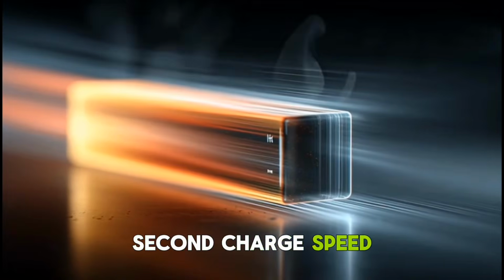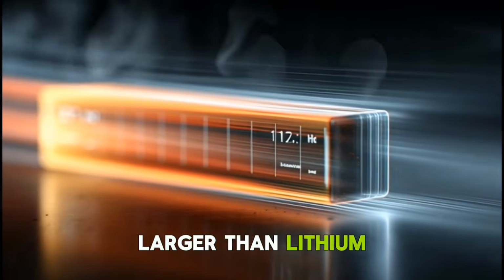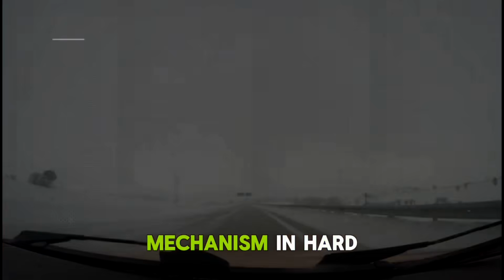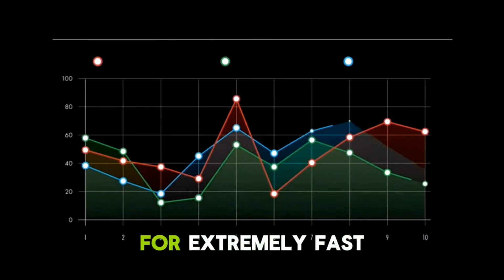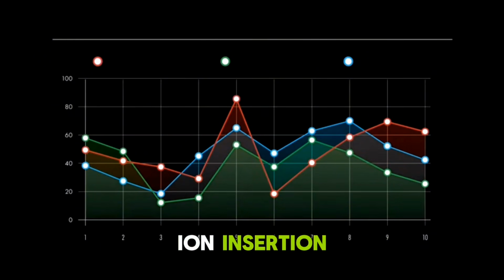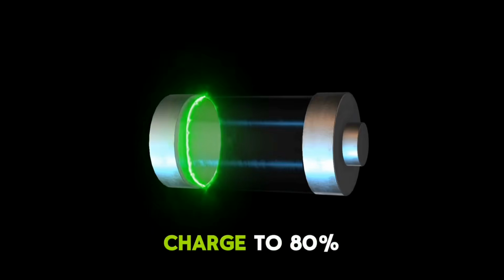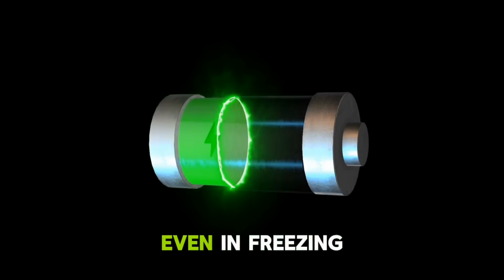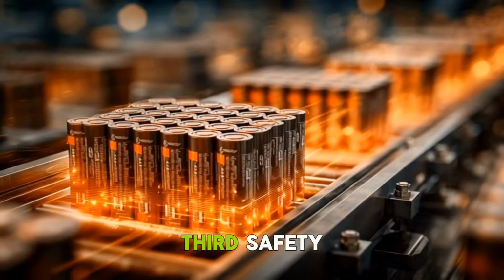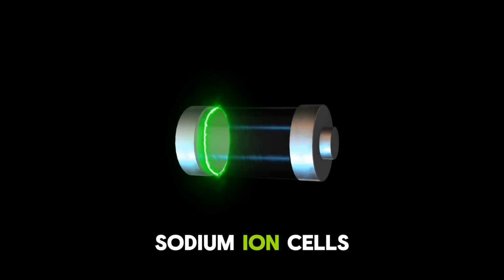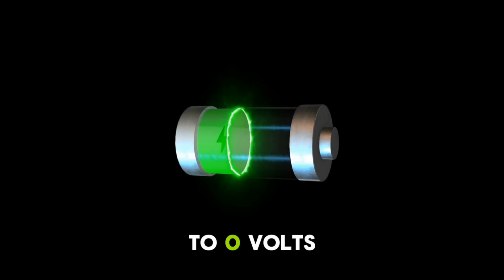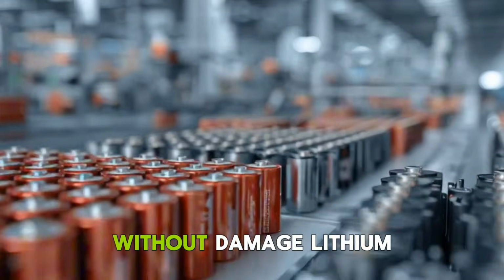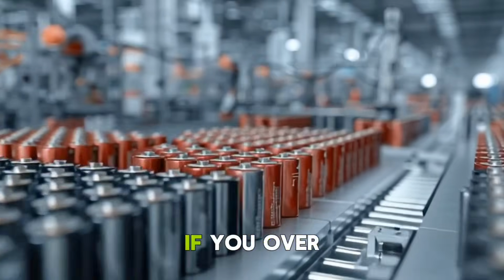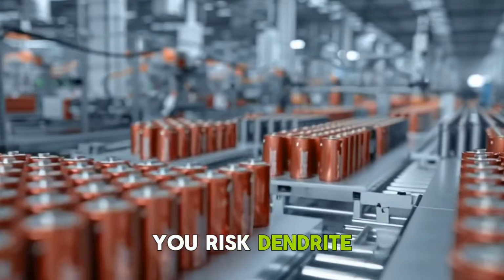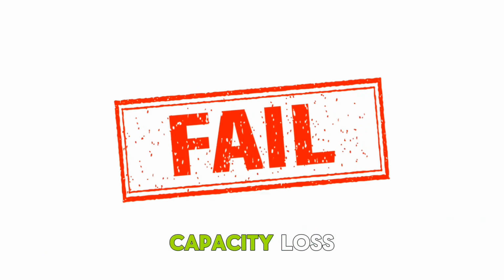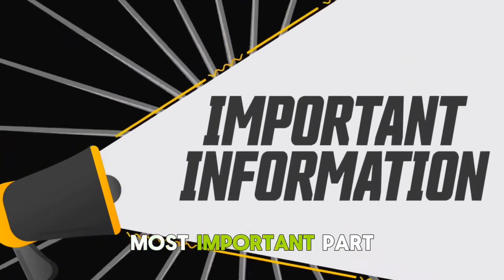Second, charge speed. Sodium ions are larger than lithium ions, but the intercalation mechanism in hard carbon anodes allows for extremely fast ion insertion. CATL cells can charge to 80% in under 20 minutes, even in freezing temperatures. Third, safety. Sodium-ion cells can be discharged to 0 volts and stored indefinitely without damage. Lithium-ion cells? If you over-discharge them, you risk dendrite formation and permanent capacity loss. But here's the most important part.